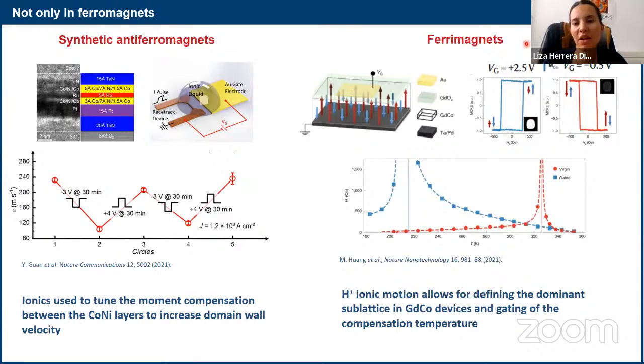magnetic moment domination, let's say, and then they could see that they could change the compensation temperature, the magnetic moment compensation, by gating, and this was done again with hydrogen mobility.